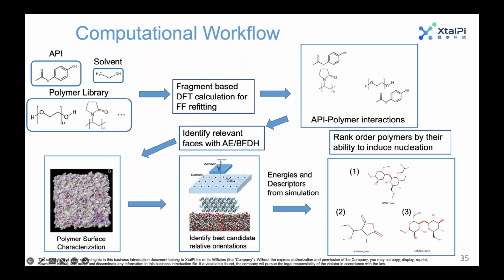And then we'll characterize the polymer or crystal surface, and we'll set up a simulation that looks something like this, where you have the template being much larger than the crystal slab, and we're going to identify and model how the crystal moves over that template. From those MD simulations, we'll get the energies of interaction and some other useful descriptors, and we'll use those to rank order the polymer or the crystal templates by their ability to induce nucleation. So that would be the ultimate output: the templates that we think interact best with the crystal and give you the best chance of nucleating that particular crystal.